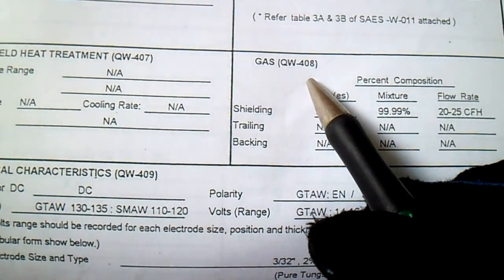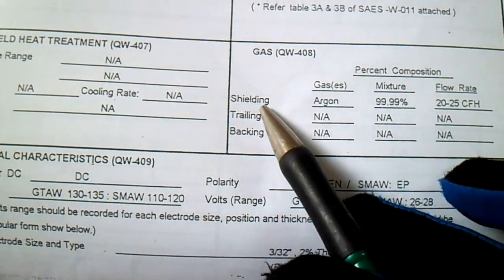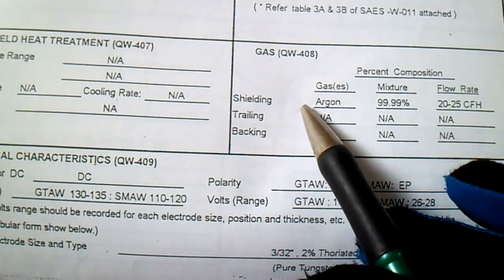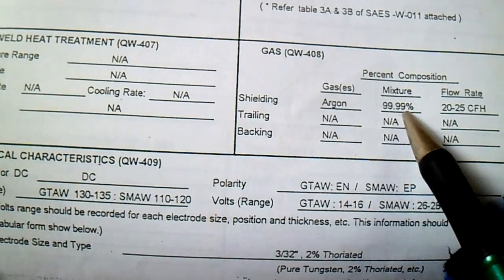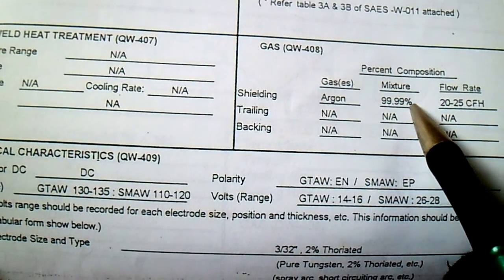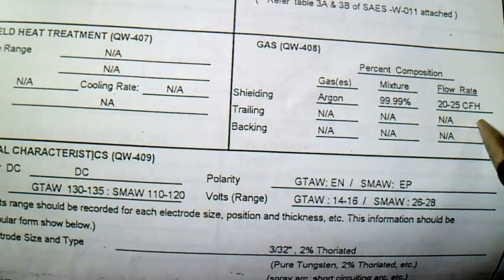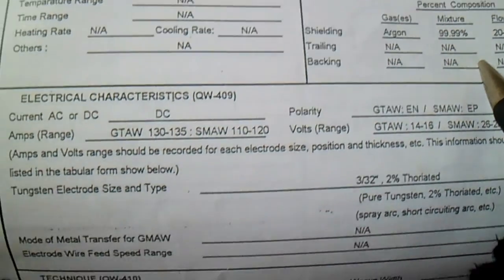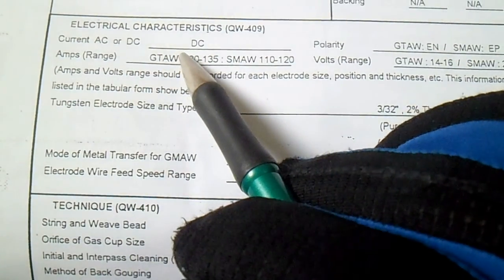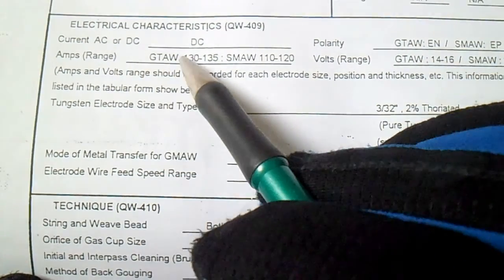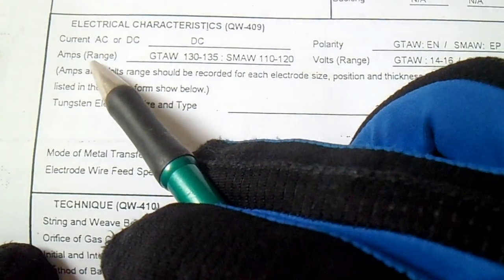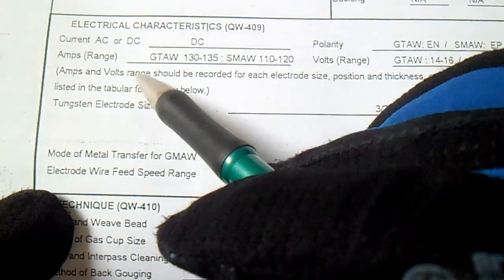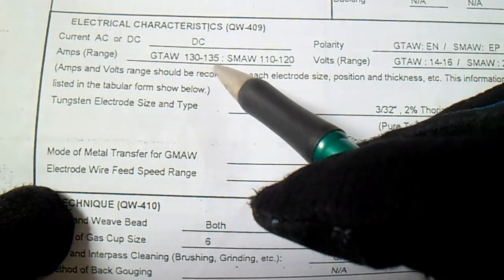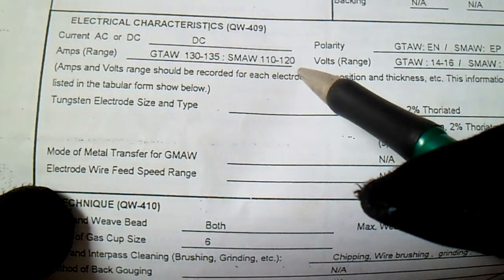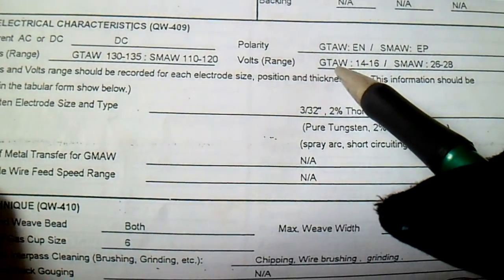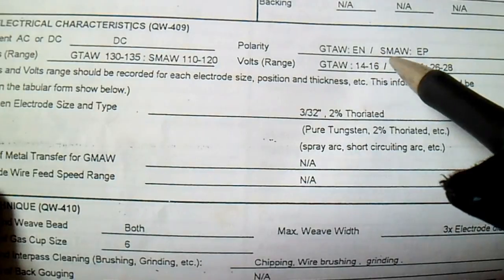Okay, and gas, this is a percent composition, from shielding, trailing, and backing. Okay, from shielding, gas is argon and 99.99% mixture. So our flow rate is 20 to 25 CFH. So we have also electrical characteristics. So this is AC or DC. So we are using DC. So amperage is GTAW 130-135 and SMAW is 110 to 120. So polarity is GTAW electrode negative and SMAW electrode positive.